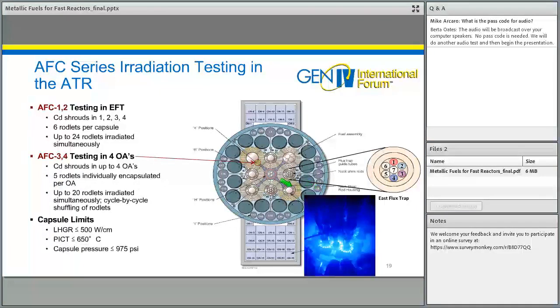Now, as I mentioned, we're doing this testing in the ATR. So these are fuels designed to fuel a fast reactor, but we've done most of our testing in the ATR, which is a thermal spectrum materials test reactor. It's not at all a prototypic environment the way it starts out, although we've modified the way we do these tests to make it a bit more prototypic.